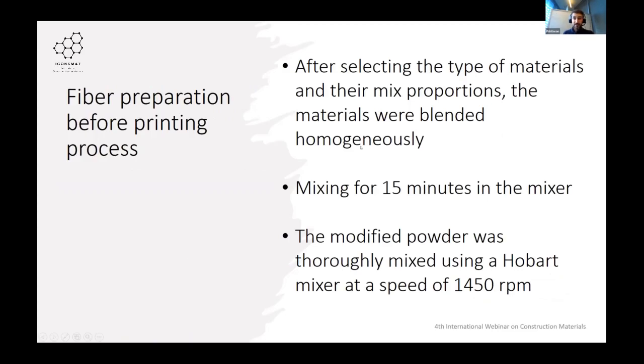As I mentioned, for the fiber preparation, after selecting the types of materials and their mix proportion, the materials were blended homogeneously, and we need to mix for around 15 minutes. Usually the speed of the Hobart mixer is about 1,450 RPM. We can go up to 1,900 RPM, but we should consider that if it's too fast, it may damage your fiber. So we should be careful while mixing.